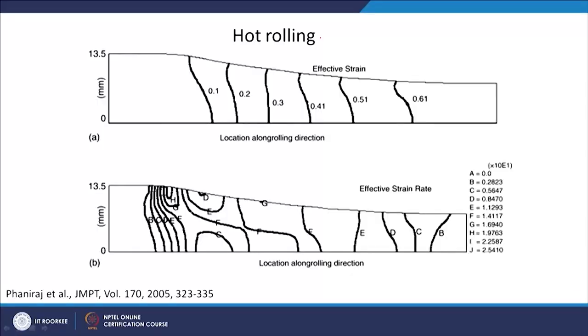There will be multiple stages. In the first stage you would like to break the dendritic structure. Then you do some annealing and you have some coarse grain structure. Then you go for fine grain structure and so on, and then you will go for cold rolling processes later on. If you see a typical deformation process during hot rolling, here I am talking about the strain distribution.